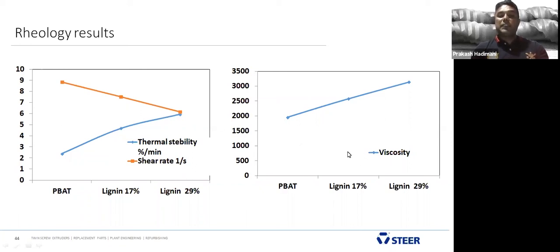When you see the viscosity, the addition of lignin increases the viscosity. When you compare to the natural or virgin PBAT, there is an increase in the viscosity. It is increasing slowly, and it goes to almost 3000.